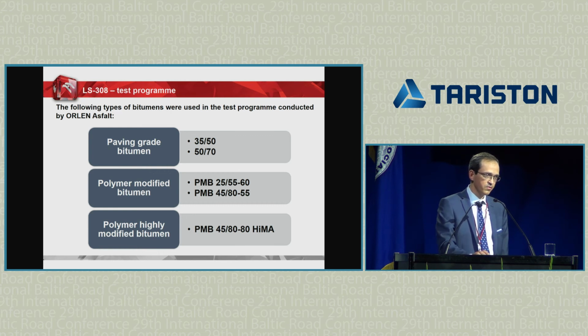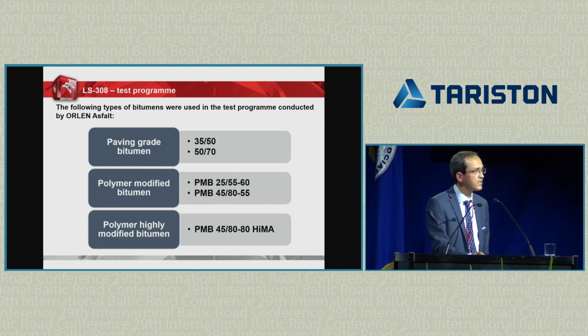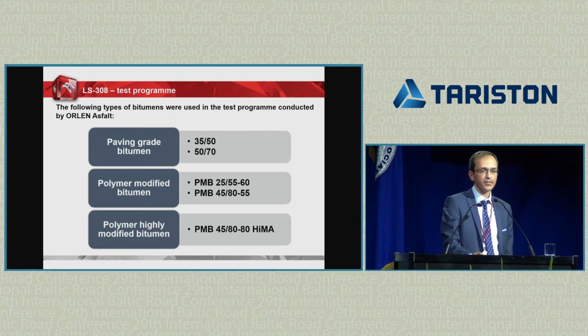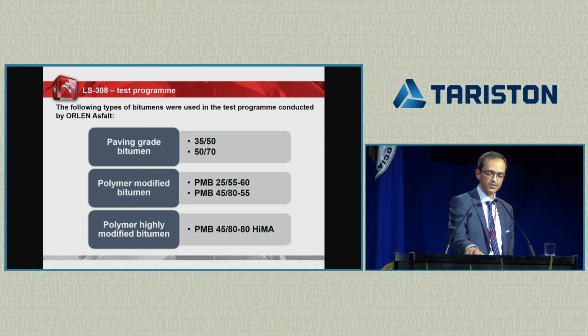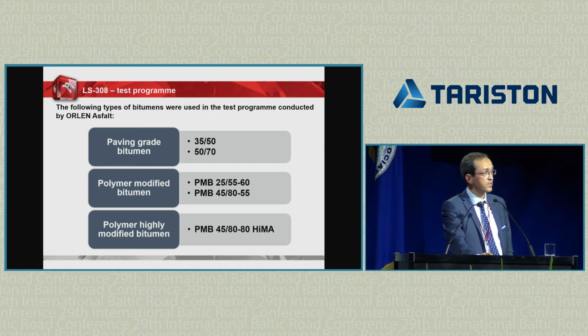But you can see on this table, on this chart, the penetration of the bitumens is between 30 and 60. So, let's say, starting from the beginning, these are very hard bitumens. And in the former presentations, with the professor from Finland, we know that it is not the best idea to use such hard bitumens in a low temperature climate.